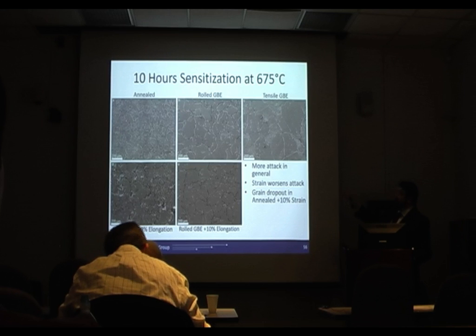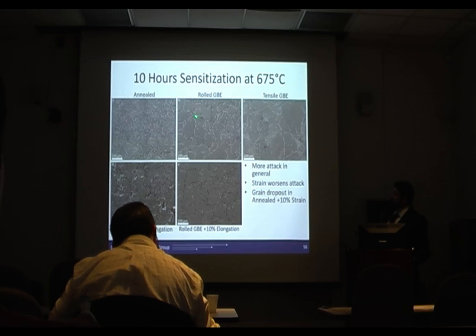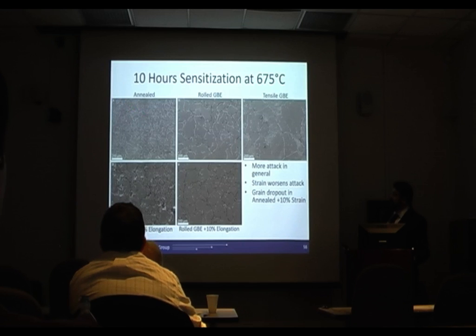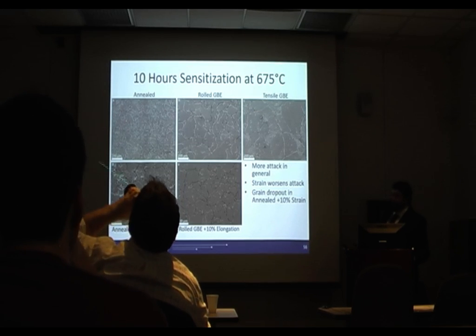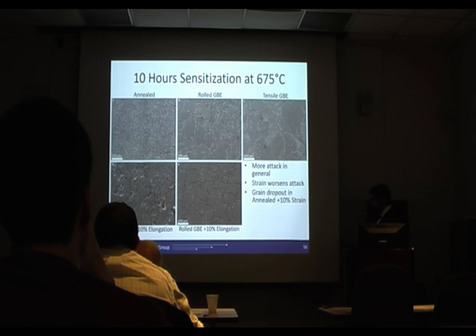I also did the 1 hour sensitized, which you'll see the data from, but honestly, in SEM, they appear pretty much identical to the unsensitized. When we get to 10 hours, we're starting to see some differences. Primarily, we see much deeper attack, shown darker in these images, at some of the grain boundaries, and especially triple junctions in the annealed. And then, especially in the annealed plus 10% elongation, we're actually seeing grain dropout occurring. So there are just holes in the sample surface where a whole grain fell out because it corroded behind it. We're only seeing that in the annealed plus 10% elongation.